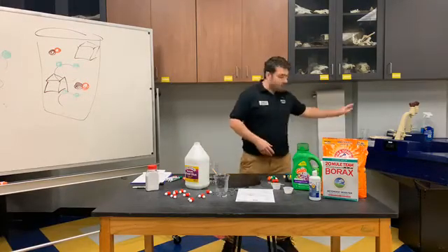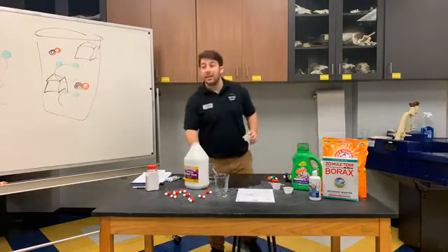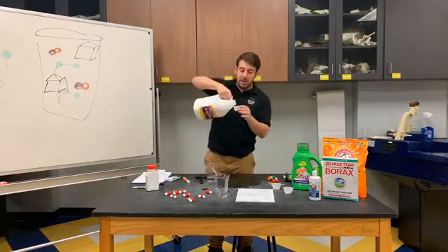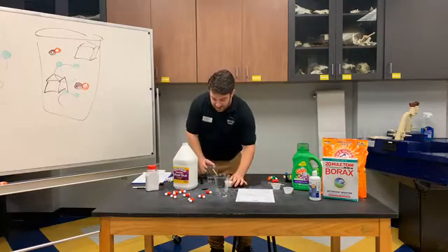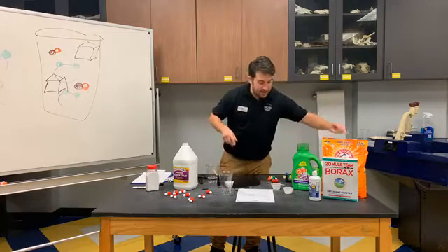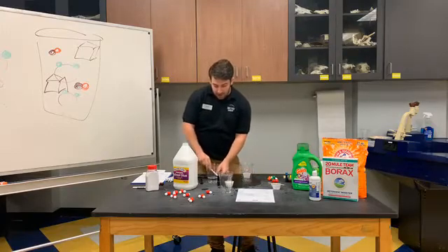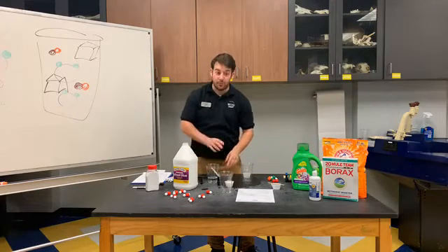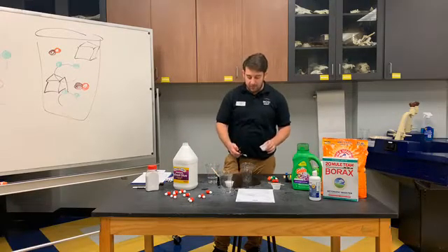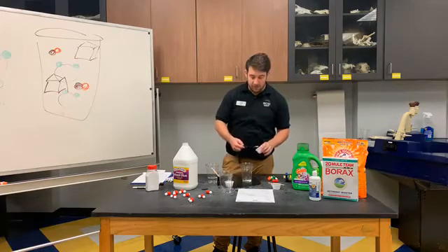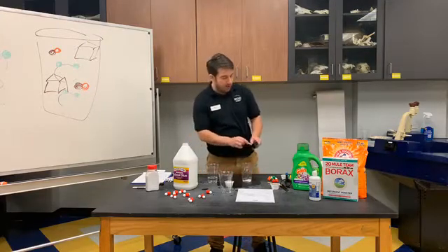The next thing that we are going to be making is the world famous MOSI Bouncy Ball. And this is actually, in my opinion, easier to make than full-on slime. So again, you take a whole bunch of glue, and I'll just make it right in here for you guys. And the interesting thing about this is that we're changing the ratio of borax to water. I'll talk about what happens chemically after we finish this one. For this one, I'm going to take the same amount of borax. I'm going to take a half teaspoon, or 2 half teaspoons, 1 full teaspoon. And then I'm going to take about 1/8 of a cup of water after I clean this out.